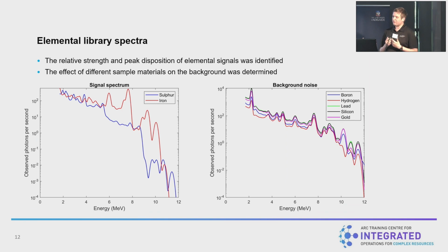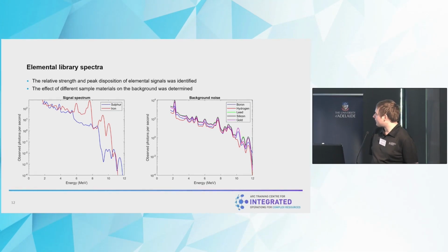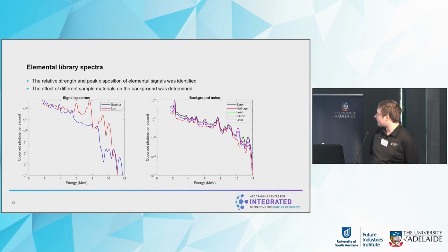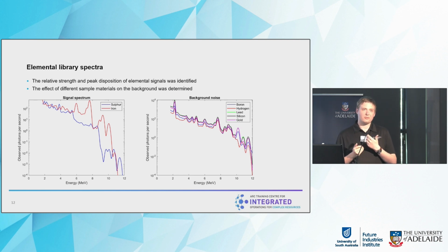So as well as the total number of photons, we can extract the relative energy spectra. As shown on the left, we can compare the signal from 30 kilograms of sulfur and 30 kilograms of iron. We can see there are differences both in the total strength of the spectrum, as well as the position and strength of the energy peaks, which is what is used to determine the relative composition of the material from the spectrum. Looking at the background, we can also see that there are complex effects of the material on the background, as the varying neutron and photon absorptions of the sample can have a complex behavior on the background.